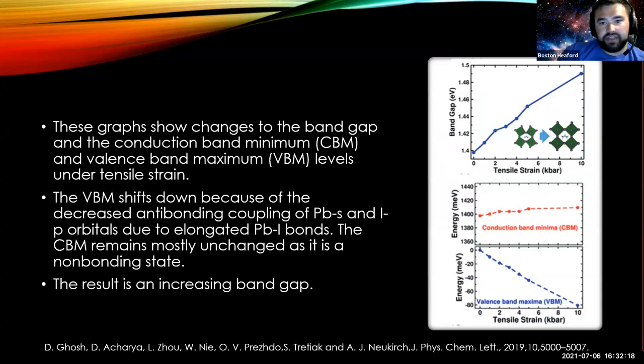thank you. And so one of the things that can change some of the properties of the perovskites is stress. In particular, this study looked at tensile strain in the material, and it showed that as you increase the tensile strain, it will start to increase the band gap, and it does that by actually lowering the valence band maximum. That changes because the bonds are elongated between the lead and the iodide in the perovskite, which this is looking at methylammonium lead iodide, which is one of many different kinds of perovskites that are often looked at. So this is one way you can modify the properties of the perovskite, by applying tensile strain.